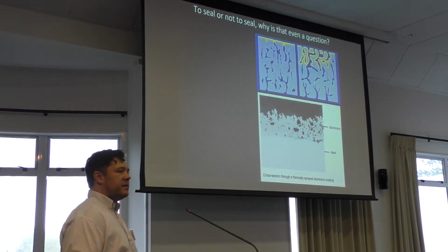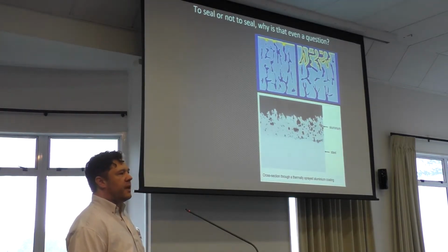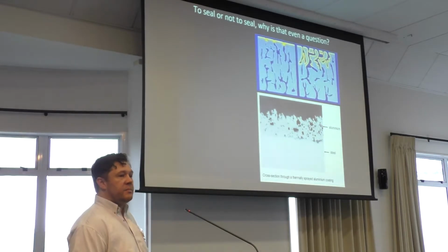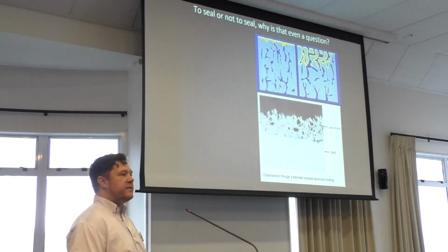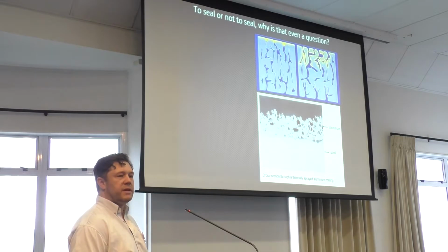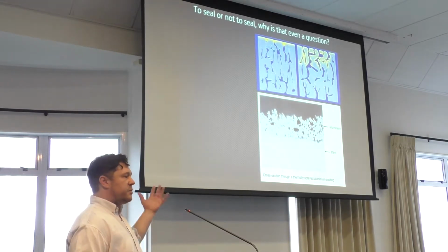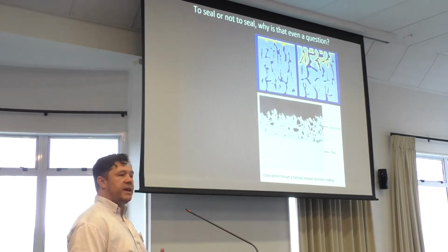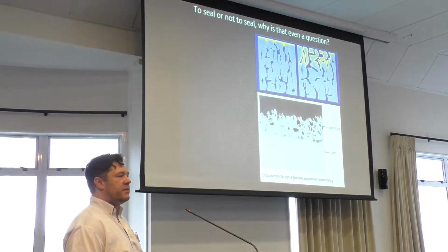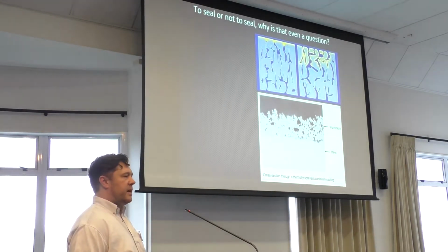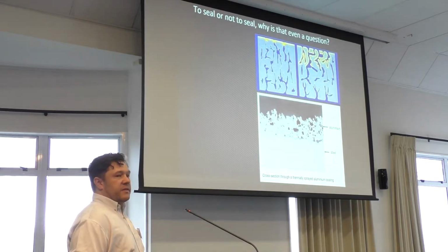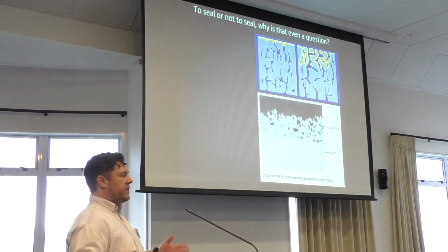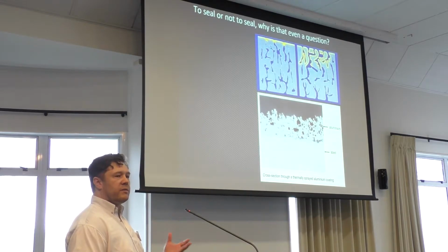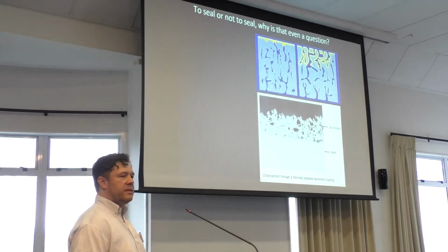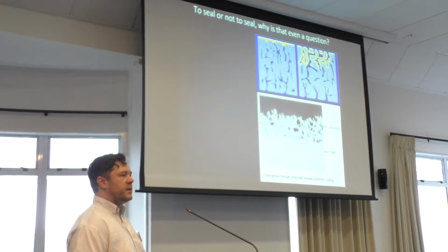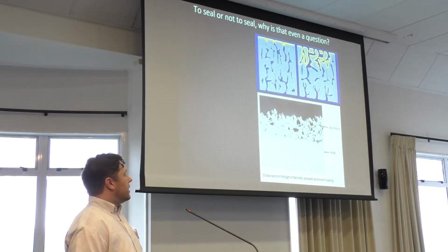So to seal or not to seal, and why is that even a question? As I've just explained, we get porosity within our coating. The standard rule of thumb is to apply a sealer directly over your metal spray to fill this porosity, which minimises the amount of air that can get to the surface of our coating and activate the zinc. If we leave it for a little bit, the zinc will activate anyway and will grow corrosion products, which are oxides, which will block the pores, and then you've sealed your coating anyway, so it's a self-sealing coating.